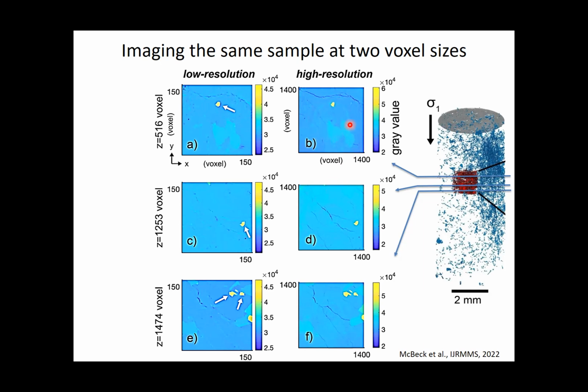There are some circular patterns here, which are artifacts of the acquisition in X-ray tomography that can be removed partly, or sometimes they are still there. And there is perhaps also, I don't know if you see it, around these bright spots, a dark area. It looks like there is a fracture at the edge of this mineral, but it's not the case. It's also an artifact of the acquisition. It's because here we work in phase contrast, and the phase contrast is enhanced at the interface between the strongly absorbing and the less absorbing mineral. So this image contains artifacts. We just have to be aware of that.